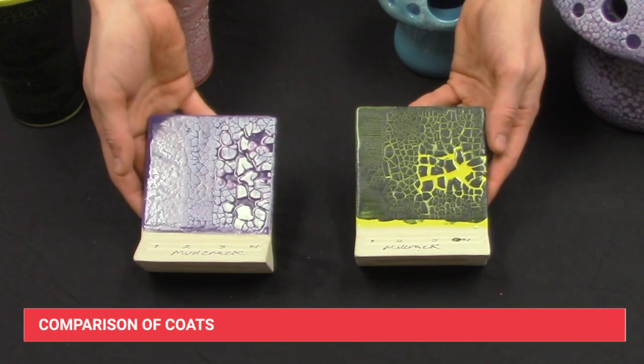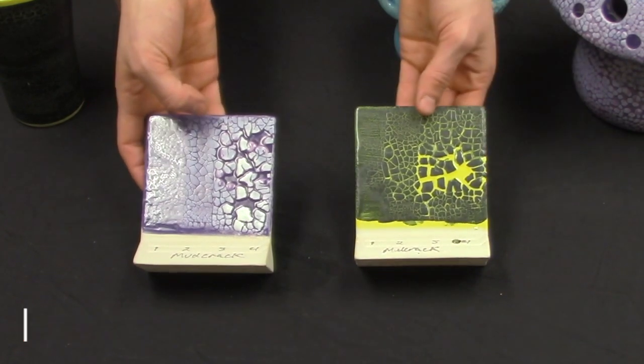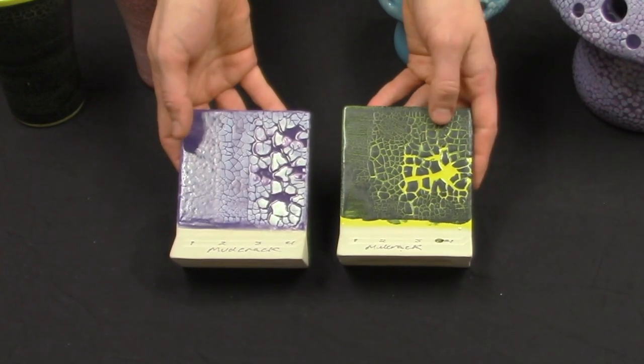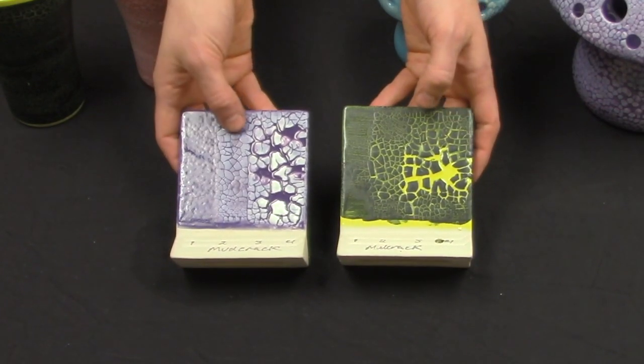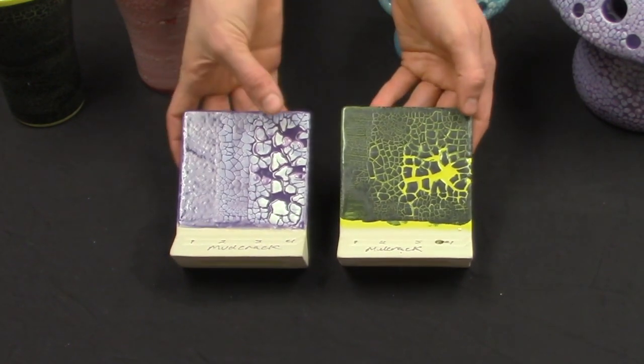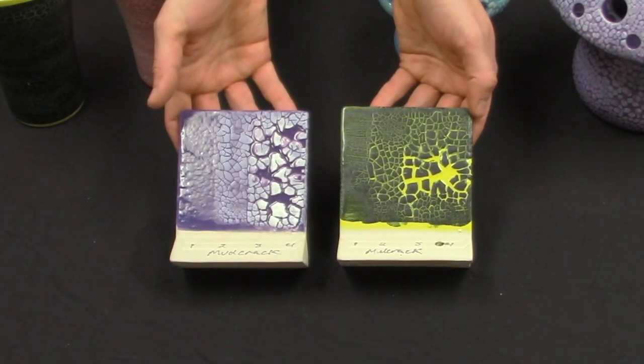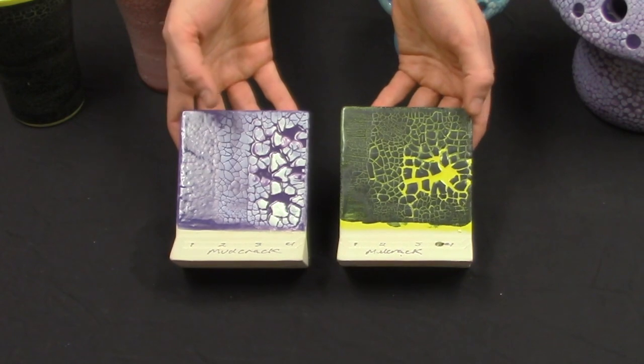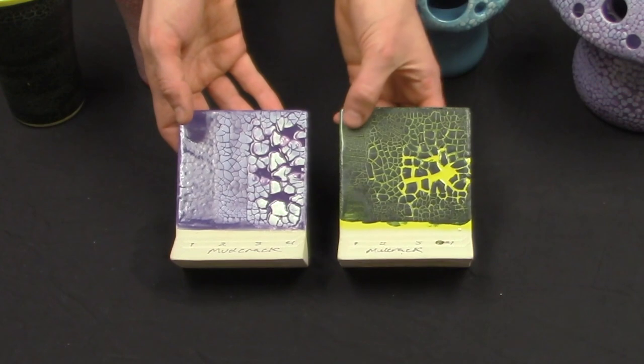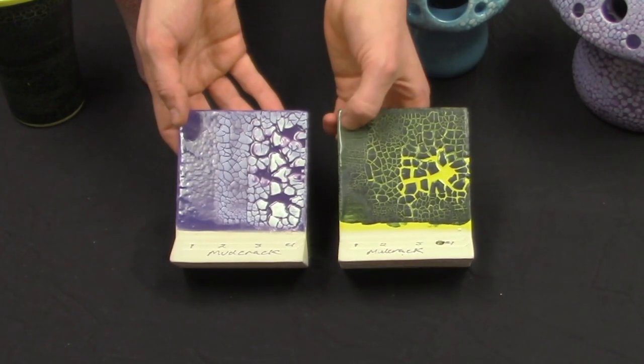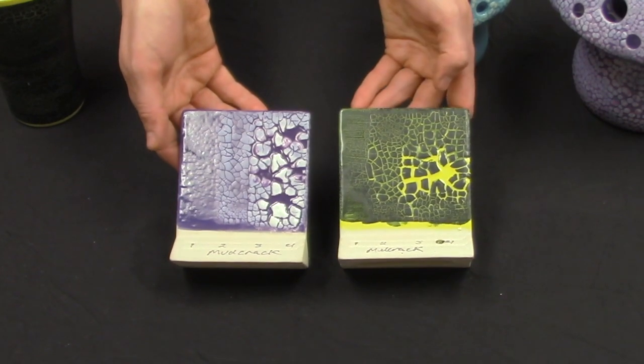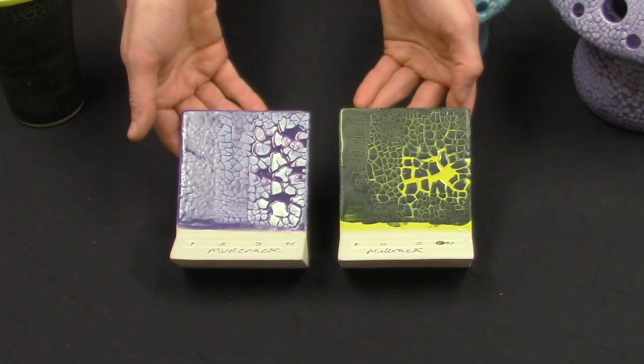Depending on the thickness of your mudcrack application, you can get variable results. Here I have white mudcrack and black mudcrack with one, two, three, and four coats each. The thicker the application, the heavier the cracking and the more raised texture in the fired results. Here it's much smoother - you can barely feel any texture, but you do get subtle mudcracking. The application affects the fired results.